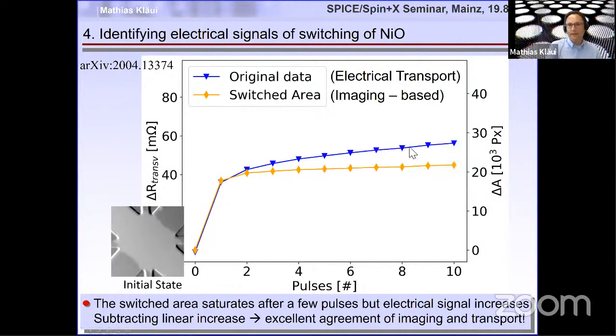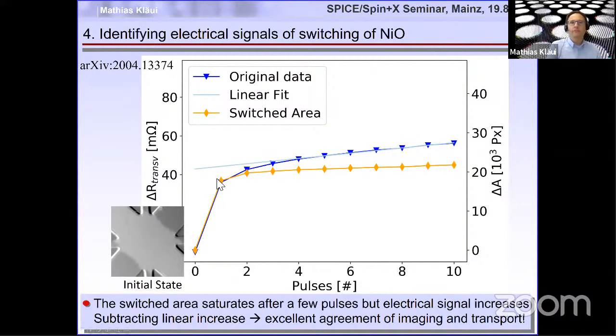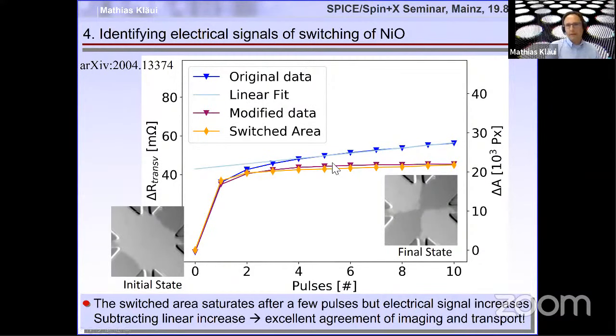So this means it's qualitatively similar, but quantitatively not the same. After a few injections, the signal from the imaging saturates, but the electrical signal continues to go up. And so we need to somehow subtract that, and we can do that. First, the electrical transport and the imaging show the same. But then after a few pulse injections, the electrical signal continues to go up, whereas the magnetic switching detected from imaging saturates. So we need to subtract this additional electrical signal, which does not correspond to magnetic switching. We do this with a linear fit, which is phenomenological. And then we get very good agreement between the switching detected by magnetic imaging and by electrical detection.